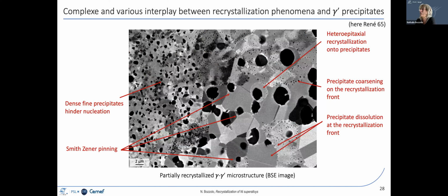We have seen the role played by second phase particles. Actually, in gamma-gamma prime alloys, the gamma prime precipitates have many more kinds of interactions with recrystallization phenomena. And I like very much this picture, which is a few tens of microns square, in which you can see many different things. Here on the left, you have a deformed grain, which could not recrystallize because of the presence of a very dense precipitation.